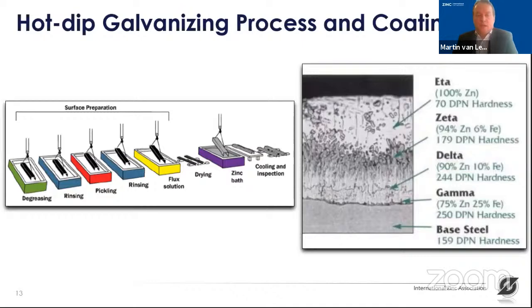A few words on galvanizing, because galvanizing will not be touched upon by my two other colleagues talking later today in this seminar, so I have a few slides on that. We make the distinction between hot-dip galvanizing and continuous galvanizing. In hot-dip galvanizing, prefabricated steel parts like steel beams, plates, angles or strips can be dipped in a zinc bath to apply a zinc coating on top of the steel.